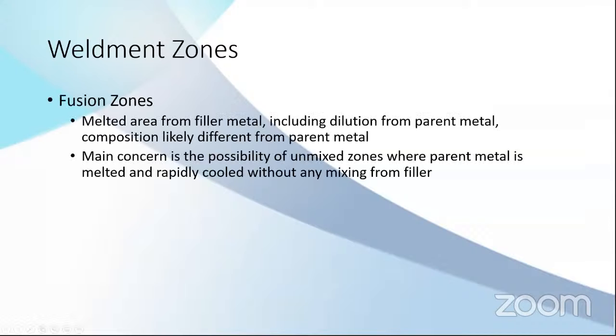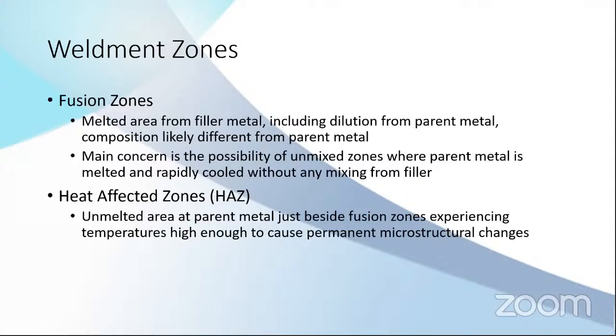And these are the weldment zones. This is a very broad explanation. So if someone has limited knowledge in welding, you can learn more by googling or reading any handbook. This is just a general explanation. There will be a fusion zone in the weldment. This is a melted area from the filler metal, including some parent metal also diluted in this fusion zone. And the main concern is the unmixed zone. There is a fusion, a melting also, but the parent metal is not diluted with the filler metal. So it's melting and then cooled rapidly without any mixing from the filler. It's like autogenous welding. And the second zone is the heat affected zone. It is the area of the parent metal that is not melted, but it experiences high temperature. So the microstructure is changed permanently.